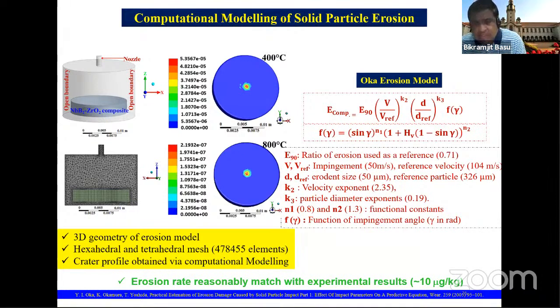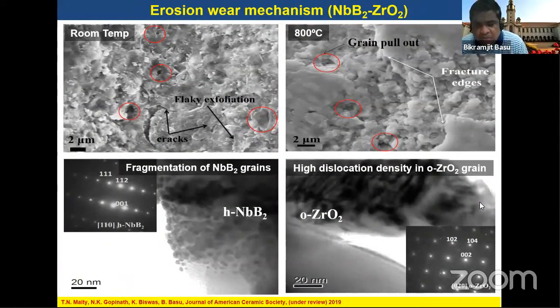We have also utilized the Oka erosion model, where we have found out what the erosion rate should be, the theoretically predicted erosion of the composites, by taking the experimentally measured values at the normal impingement angle, which is E90. So V and V reference are the impingement speed, like 50 meters per second, and the reference velocity is 104 meters per second, and all of the parameters are mentioned. What is important to mention here is that, following the Oka erosion model, the theoretically predicted erosion rate closely matches the experimentally measured erosion rate, at least in this case of niobium zirconia composites.